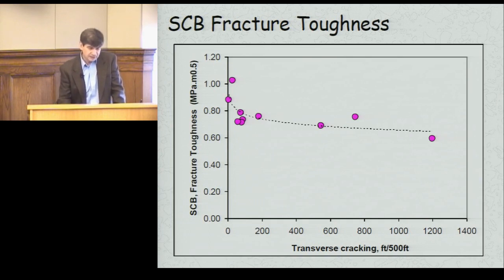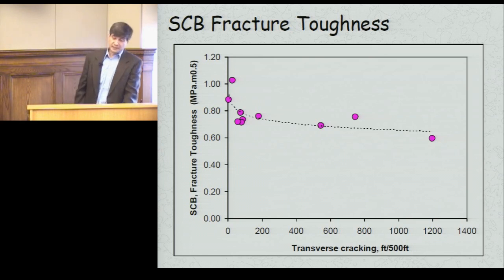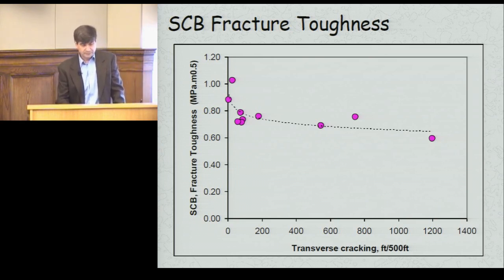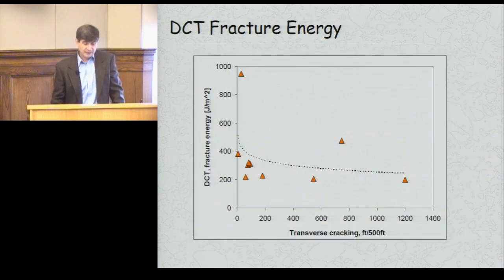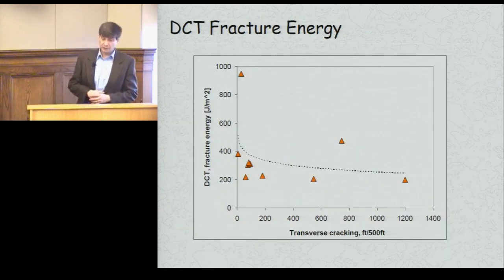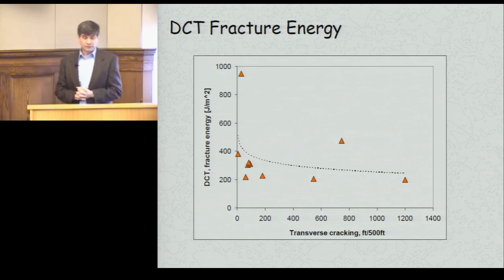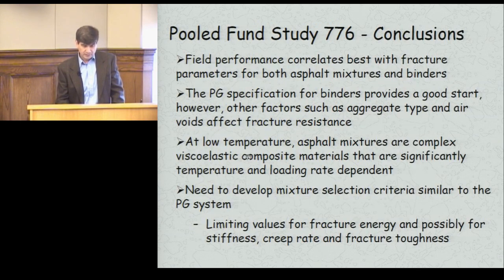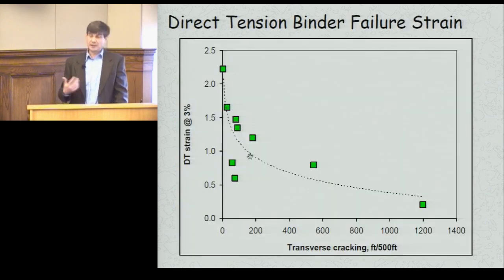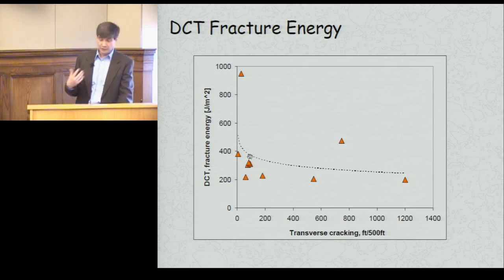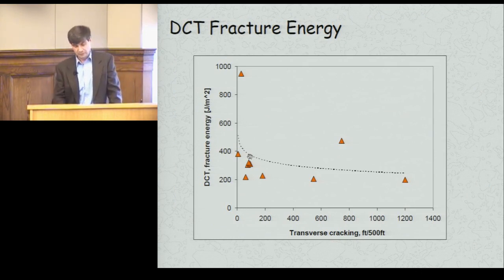Similarly, for fracture toughness, there is a correlation, maybe not as clear because there are a lot of points here, but we hope with more data that becomes available to perfect these plots. This is DCT. My colleague at the University of Illinois who developed this plot for DCT has additional data from other projects, and they also found out somewhere in the vicinity of 300 to 400 is probably a good limiting value to set up as a threshold for asphalt mixtures.